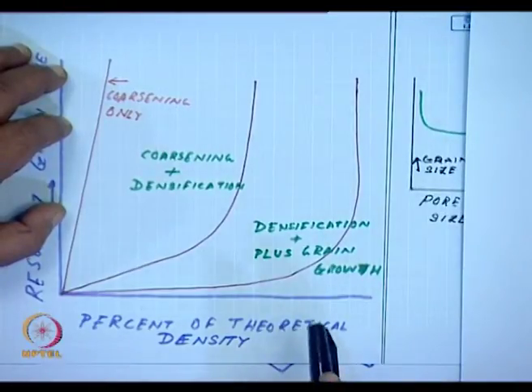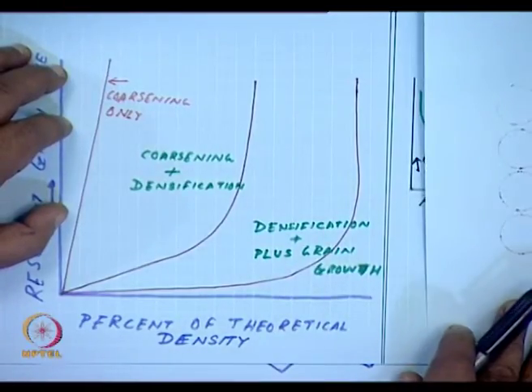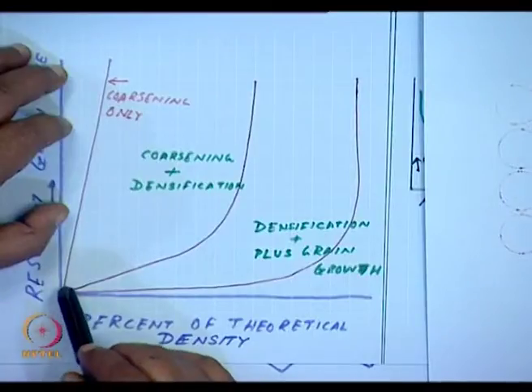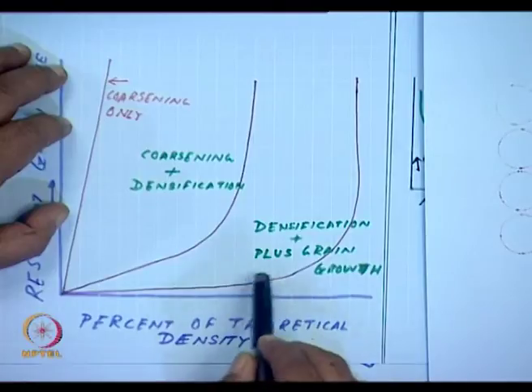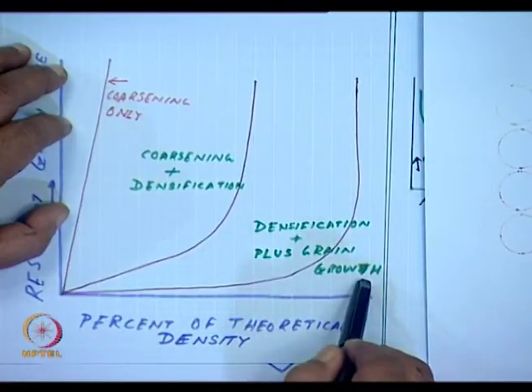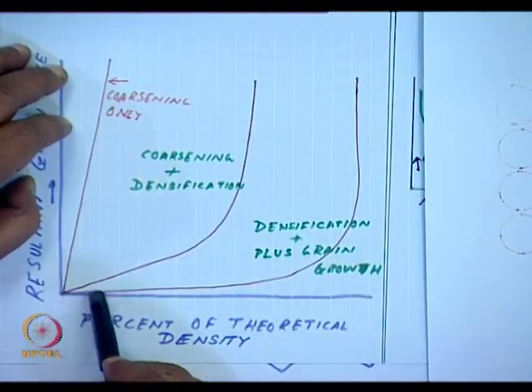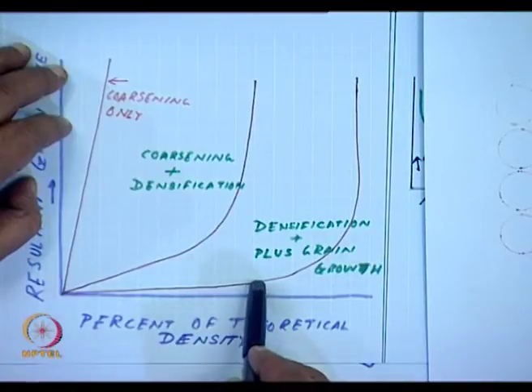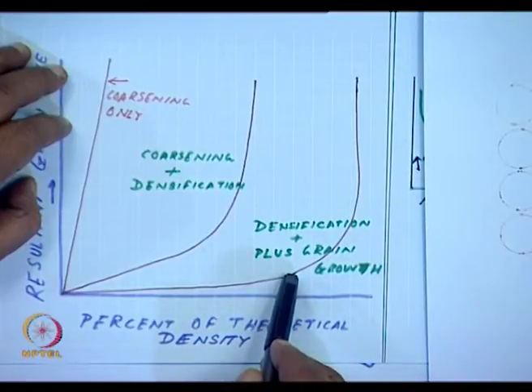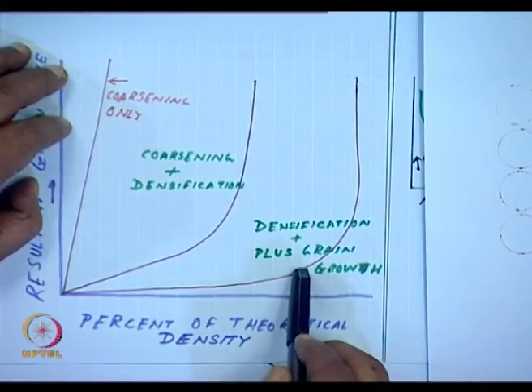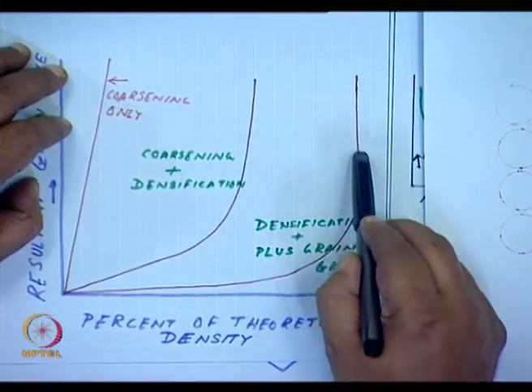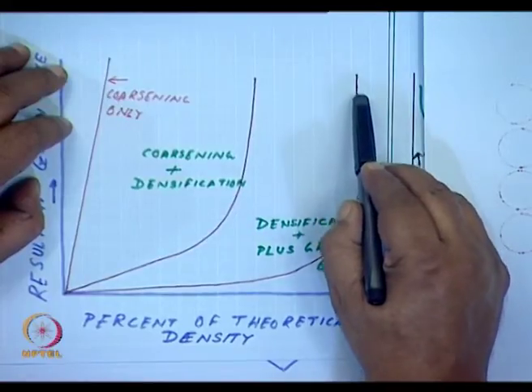If, on the other hand, I have got good sintering, what we will see is this curve: densification plus grain growth. First, as the densification occurs, the density increases. And then, when grain growth takes over, the theoretical density has been reached and the grain size increases.